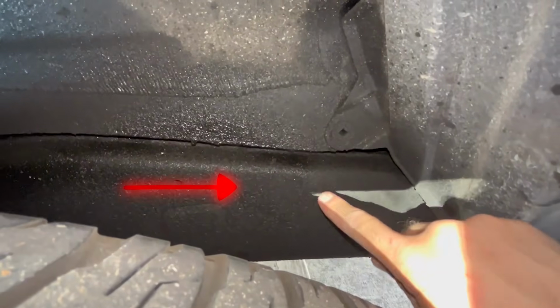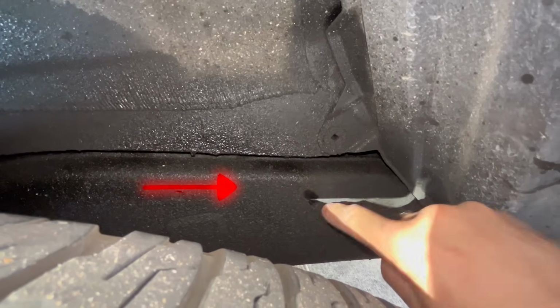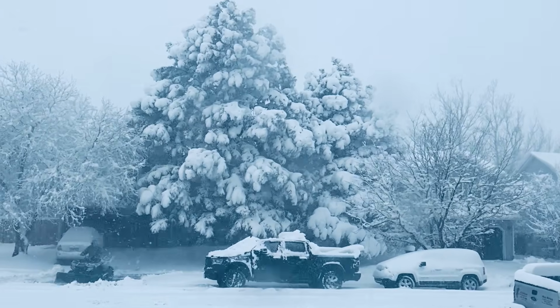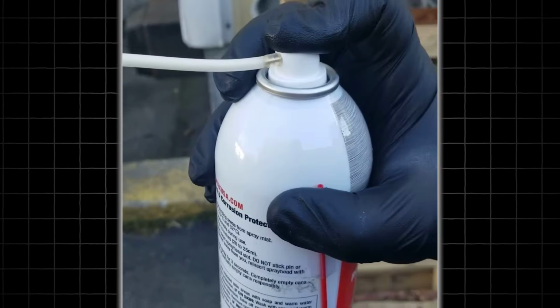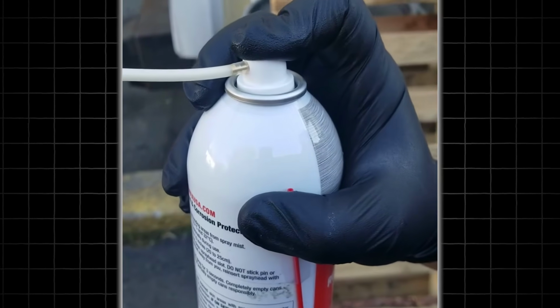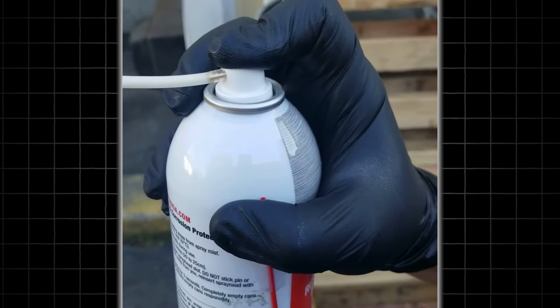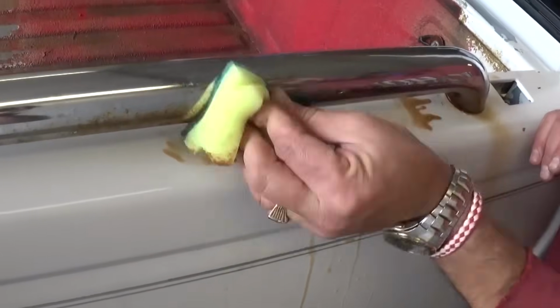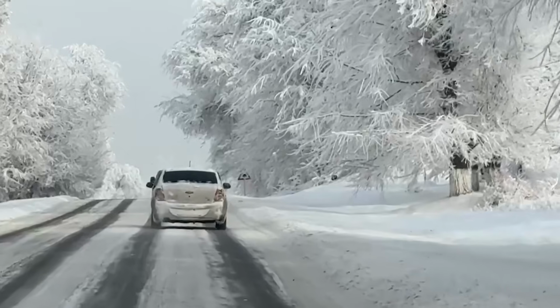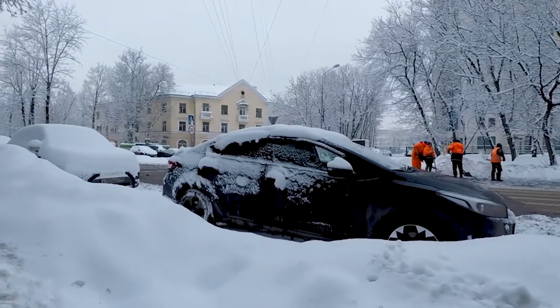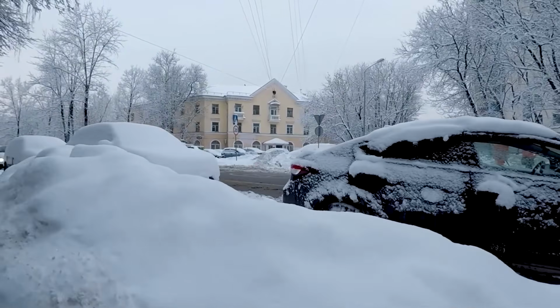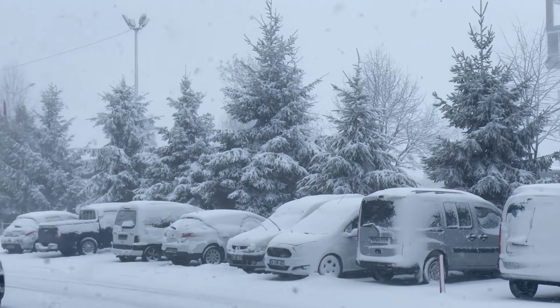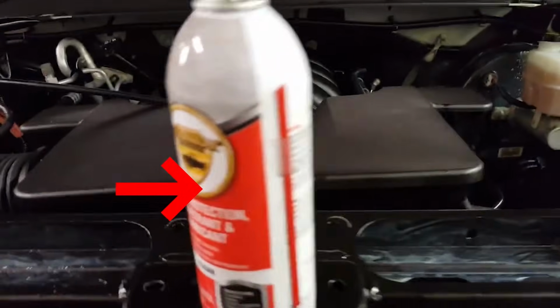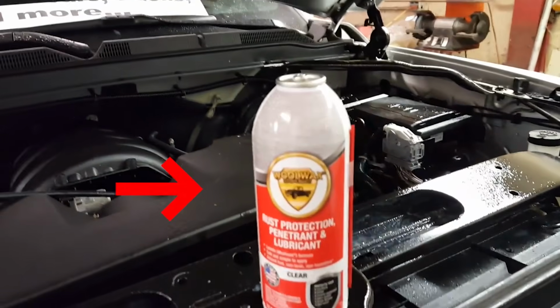Our test panels confirmed David's experience at the controlled testing level. At temperatures below -10 degrees Fahrenheit, the Woolwax formula provided meaningfully less protection than either of the rubberized formulas. This was despite its superior performance at moderate temperatures. For drivers in moderate winter climates, Woolwax is worth considering. For drivers in severe winter climates with sustained negative temperatures for weeks at a time, the cold temperature vulnerability is a critical limitation. It eliminates this product from serious consideration entirely.